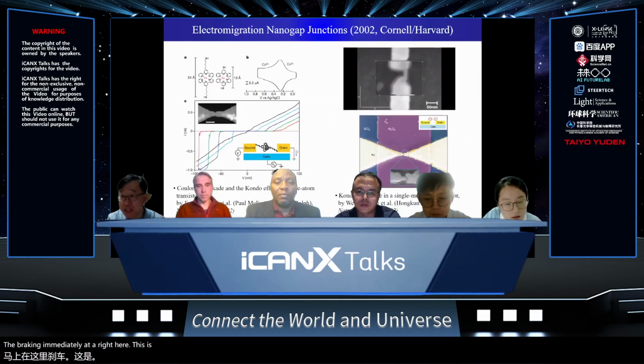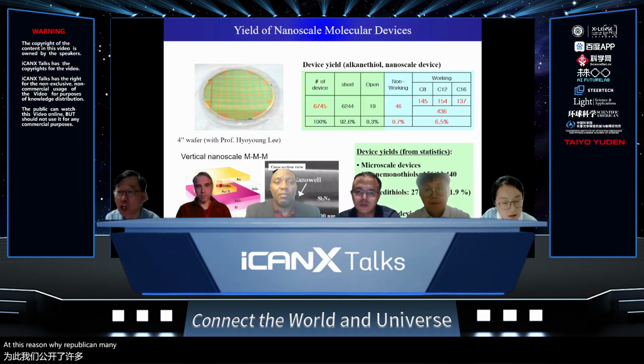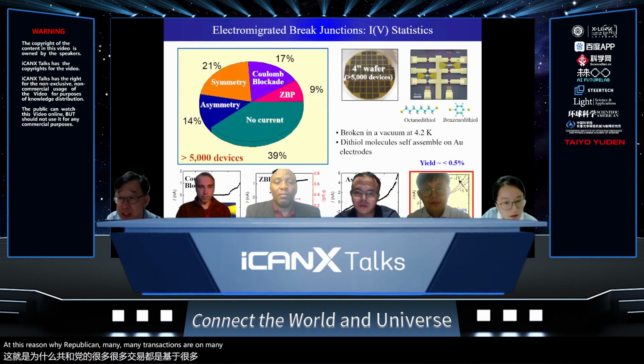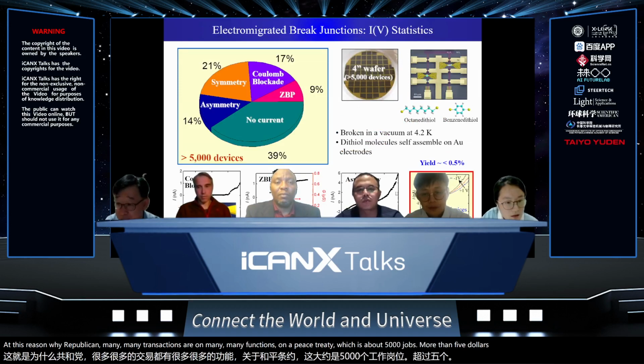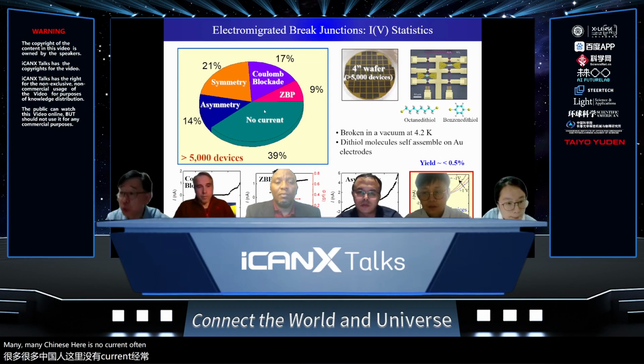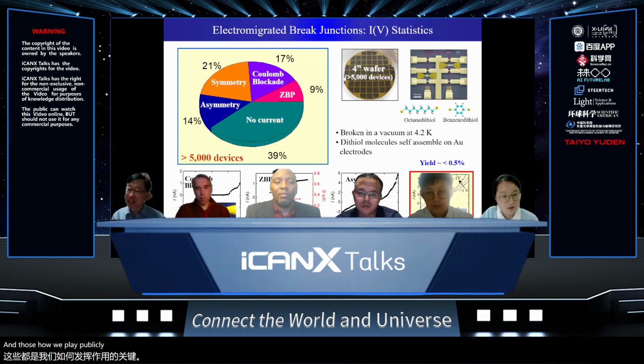This process is probabilistic, and that's the reason why we fabricate many junctions, more than 5,000. Many of them end up with no current, open, too wide, or too short, and then there's something in between, and we collect that, and then we train the device, and end up with about 30. So this is how we fabricate. It's not an easy technique. I can say it is not easy.